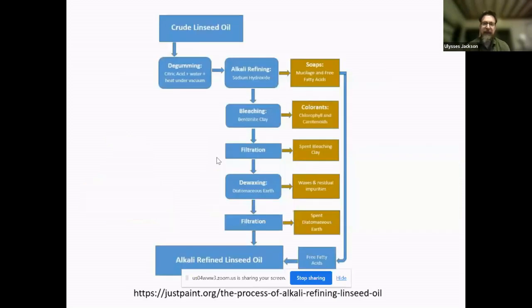We in manufacturing generally use refined linseed oil. For time's sake, I'm not going to go through this graph completely, but we do have on our justpaint.org website a really good article on refining it. The two parts I'm going to mention is that it is alkali refined, which gets rid of a bunch of the stuff that could cause yellowing. But one of those things, the free fatty acids, they need to add a little bit back in because it really helps with pigment wetting. And so when you're buying an alkali refined linseed oil as a manufacturer, you actually specify your acid value for the goal you're after.